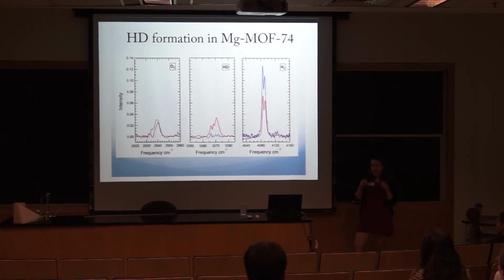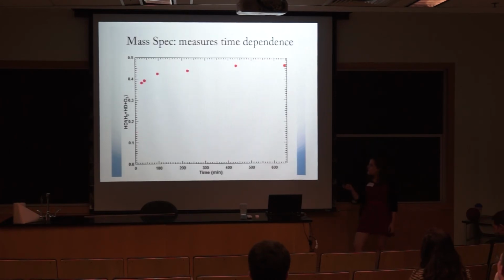So obviously something's happened, like the gases have separated and a hydrogen atom has been able to bond to a deuterium atom. We weren't expecting this because the sticking of the hydrogen molecules to the MOF is via a weak van der Waals interaction, so a dipole-dipole force, and you wouldn't expect that to be strong enough to pull hydrogen apart. We wanted to get a sense of how quickly this was happening. Since we can only see things when they're cold, we can't see the conversion. So we took our sample over to a professor in the chemistry department who has a mass spec, and he did this. So you can see, this is a plot of the fractional HD composition in the gas versus time.